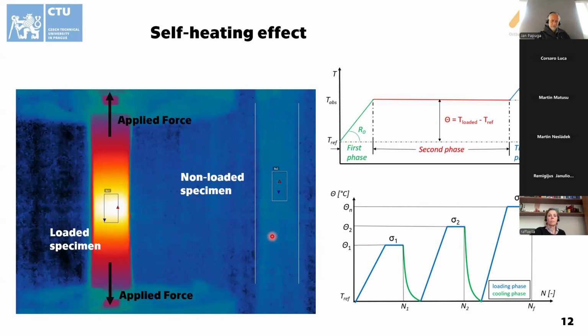About the self-heating effect. As Luca mentioned, during cyclic loading of a specimen or metallic structures, usually the loaded sample, as you can see on the left, when there is applied force on the loaded specimen, the self-heating effect or temperature increase acts in 3 phases. The first phase is basically described with a rate of temperature. The second phase, which is probably the most important in this presentation, is the stabilized temperature, and the latter phase could be described as the rate of temperature as well.